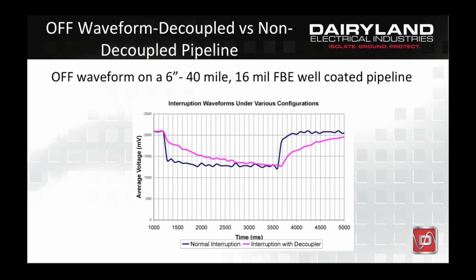Similarly, the contribution of the pipeline capacitance to the C part of the RC time constant will vary with pipeline length and diameter, but is opposite that of the resistive component. That is, the capacitive contribution of the pipe coating increases with longer and larger diameter pipes and decreases with shorter and smaller diameter pipes. This pipeline capacitance adds directly to the decoupler capacitance in the circuit RC time constant. For the example shown, the pipeline capacitance was determined to be approximately 14% of the total circuit capacitance on this rather small diameter pipeline, but will be considerably greater in larger and longer pipelines.